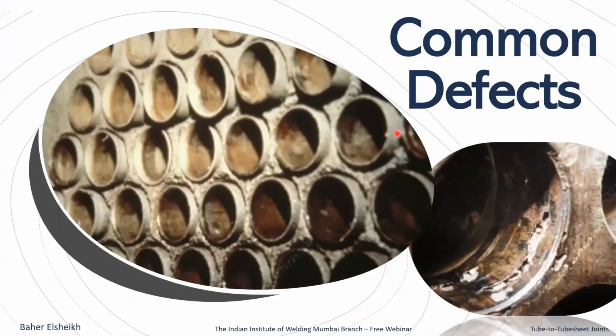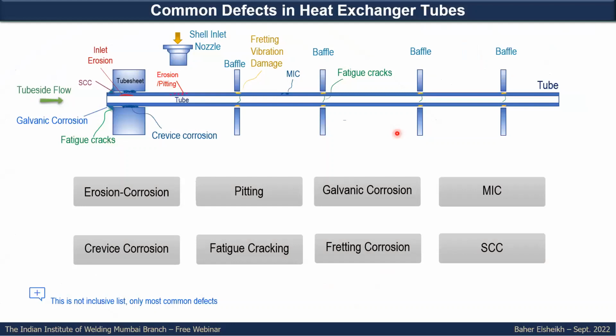Now this section will talk about the common defects which you can see in the tube to tube sheet joint. This figure shows the most common defects in the tube as a whole and in the tube sheet, and we will focus here mainly on the area of the tube to tube sheet joint, where maybe you have galvanic corrosion, or inlet erosion. It might be in the first part of the tube, and also might be in the face of the tube to tube sheet joint. We might have stress corrosion cracking, and crevice corrosion from the shell side might also affect the joint.